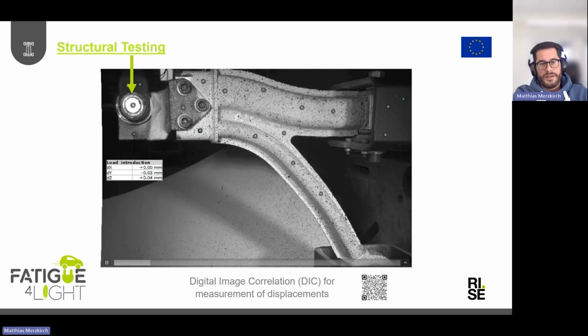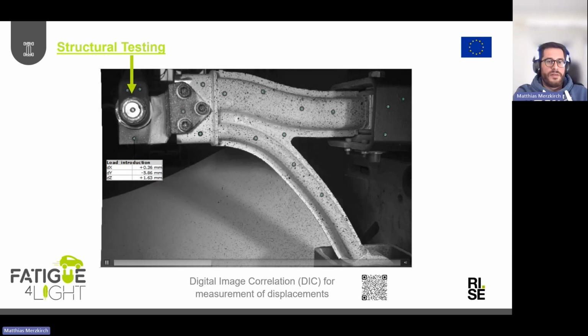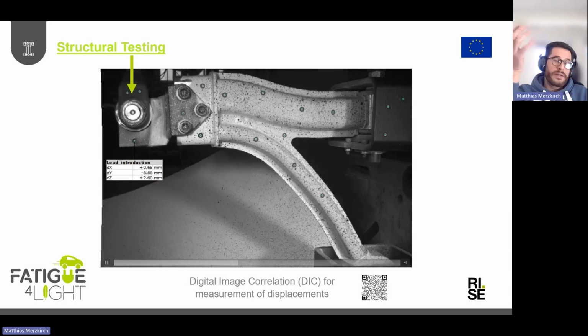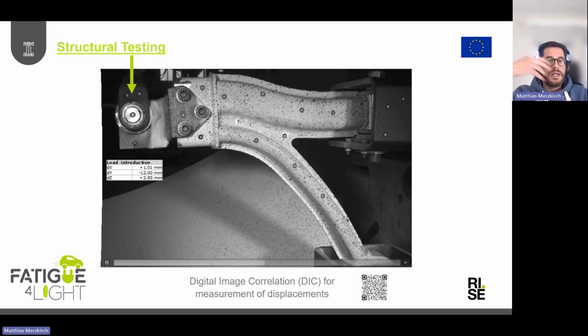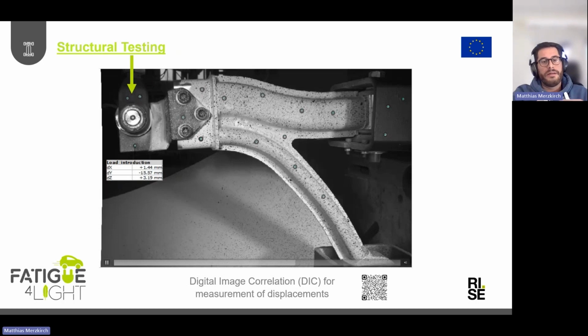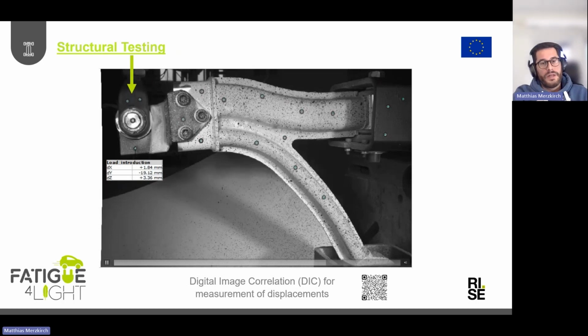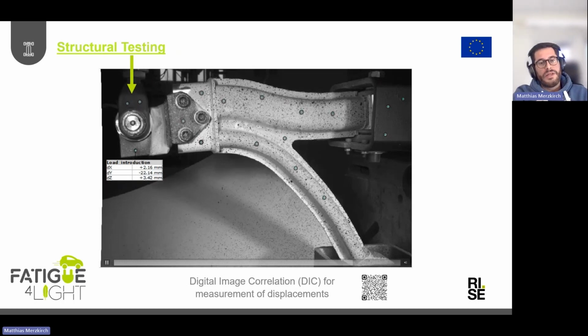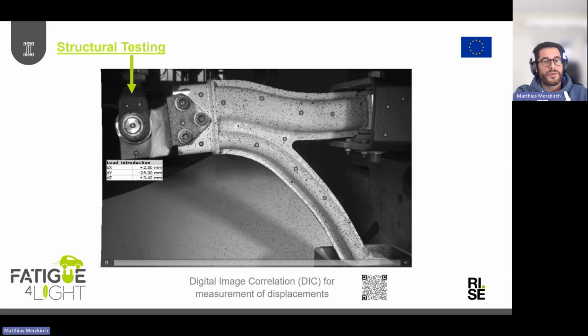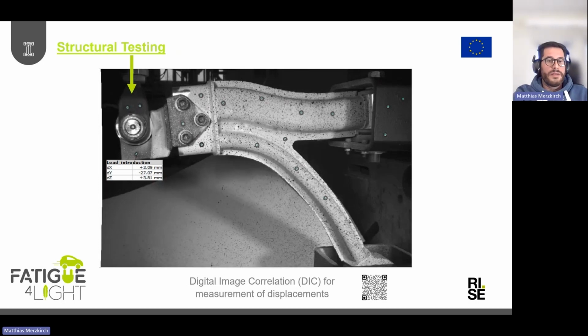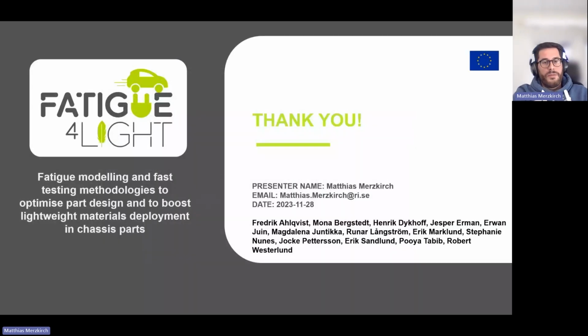So if you focus in this area here, well, we kind of neglected the weakest link, and the weakest link here in this case is definitely the adhesive joint between the flat plate and the 3D laminate. So here you actually see this kind of debonding that's happening, and then also leading to an instability of the structure. And with that, I thank you very much for your attention.